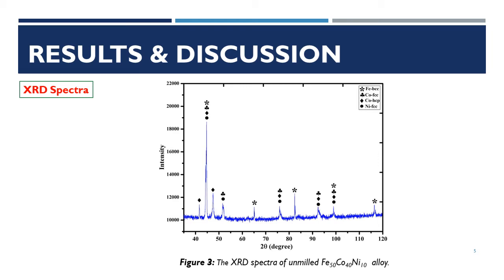The iron BCC phase possesses 5 main peaks with high intensities and narrow widths, while the minor peaks correspond to cobalt and nickel. In this beginning mixture, the three phases have overlapping peaks.